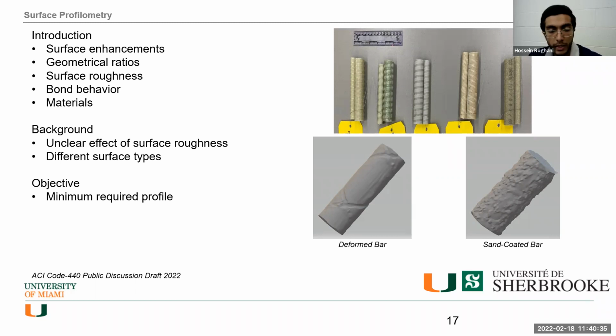So we have 5 different surface profiles in this study, with 2 different diameters. They are number 5 and number 8 bars. In this study, we will consider the surface enhancement. We will measure the geometrical ratios, the surface roughness, bond behavior, the materials characteristics, which can really affect the entire result. And yeah, okay. In terms of the bond and the surface profile, you can say a bar surface deformation or the texture is induced so that the mechanical bonding is developed between this deformation and the texture can affect your mechanical bonding, which develops between the fiber reinforced polymer rebars and the concrete. So this study will investigate the minimum roughness requirement for FRP rebars to guarantee the requirement of the bond